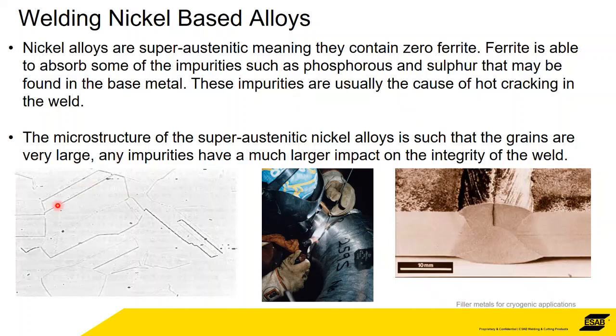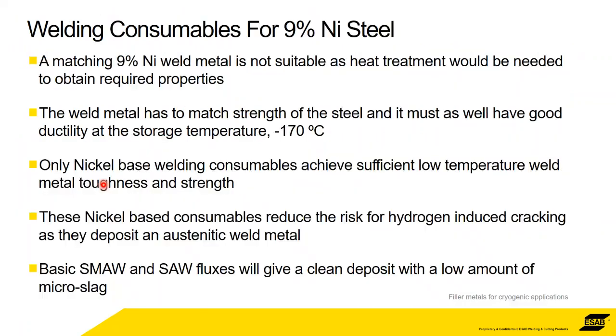And also what we should realize is the microstructure of these nickel alloys. They have very, very large grain sizes compared to other steels. So the large grain size means they've got very few grain boundaries, and, explained in a very simple fashion, it's the grain boundaries that lock together that create the strength within the microstructure. Grain boundaries lock together, they bump into one another, they tie together, and that's what creates the strength. With the nickel alloys, they've got very big grains, so very few grain boundaries in comparison. So any impurities in here have a much larger impact on the weld metal than, say, in a 316. So you have to be careful with that.